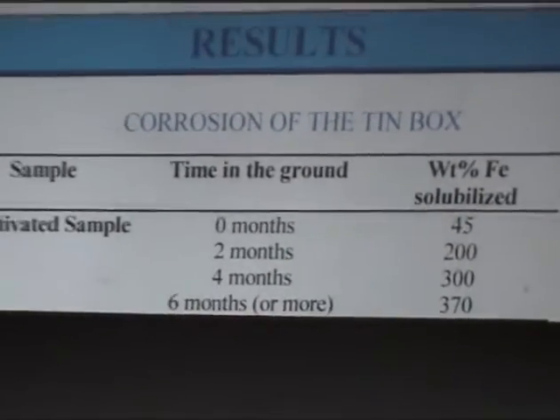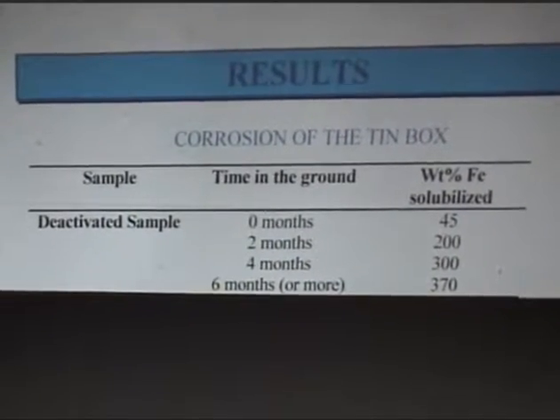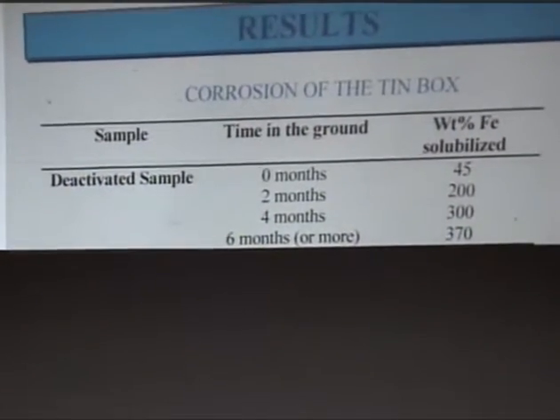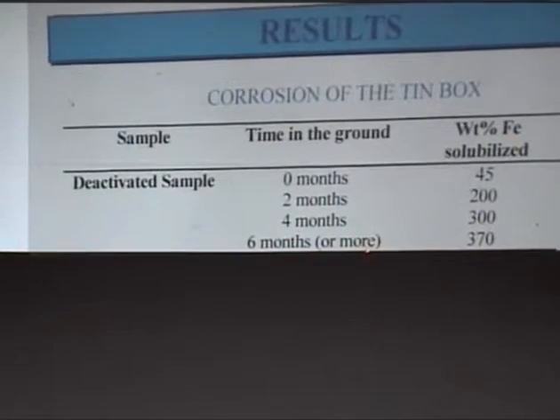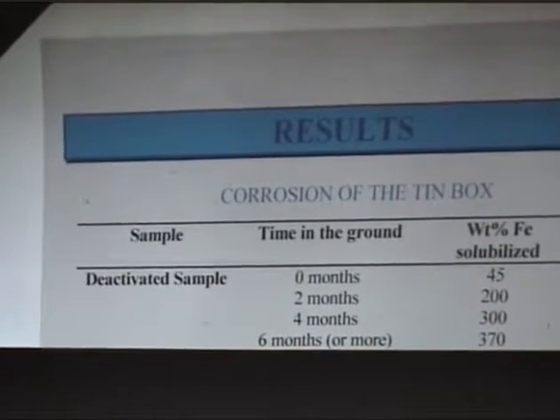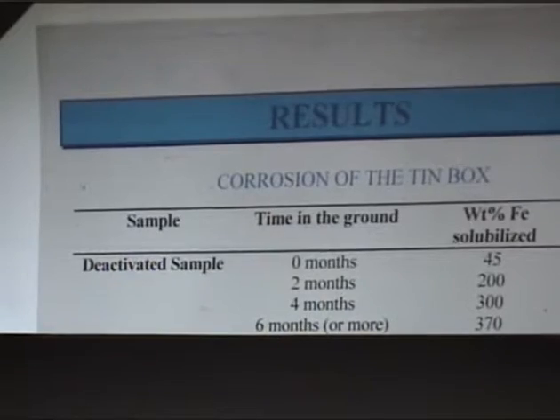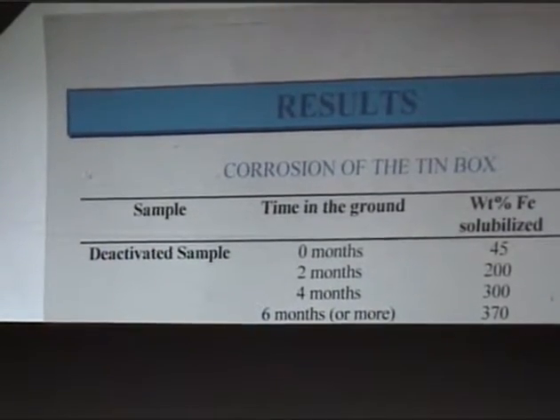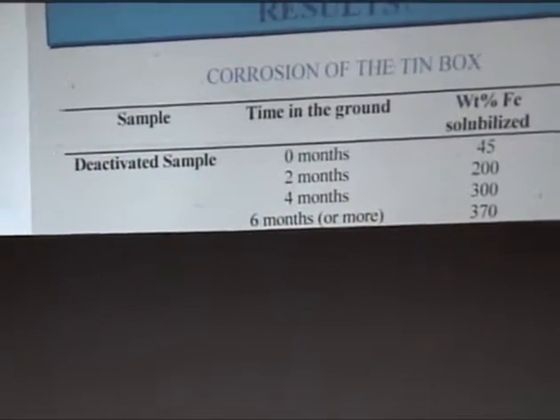Of course, if the catalyst was placed into a tin box, this box is subjected to corrosion over time. In fact, for the deactivated sample, an extensive corrosion of the bottom and also the lateral, internal walls of the box was observed. Therefore, the solubilization of iron was much higher than the total amount present in the deactivated catalyst.